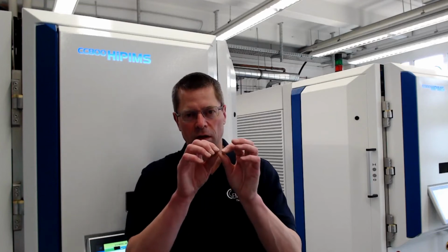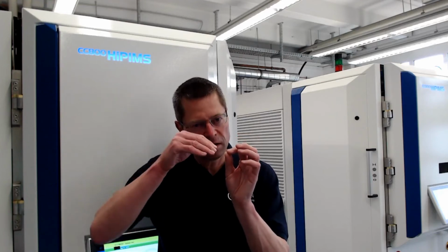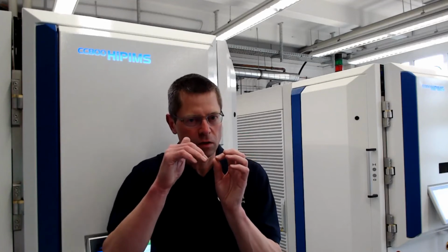The typical thing you see in an arc coating is that on a cutting edge of an insert, you have some kind of an undercut because the field lines concentrate there, and over edge or damage the cutting edge. This you will not see in HiPIMS because it's by far easier to control and to adjust power. That's the reason why for things like sharp grooving inserts or small, very pointed micro tools, HiPIMS is by far easier to control than large machines.